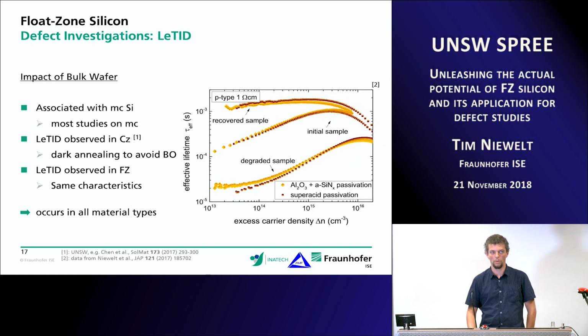We've also tested whether the degradation actually occurs in the bulk. So here you see a comparison of 3 samples at different stages in this degradation. So we have an initial sample, a degraded sample, and a recovered sample, and it was always measured with a typical aluminum oxide silicon nitride passivation stack. Then this was etched off and passivated with the superacid passivation at the University of Warwick. And we see that we really basically get the same lifetimes with both passivation schemes, although we etched away quite a bit of the surface, indicating that it's really a bulk defect. And that it is quite likely caused by the PERC process because it's not there otherwise.